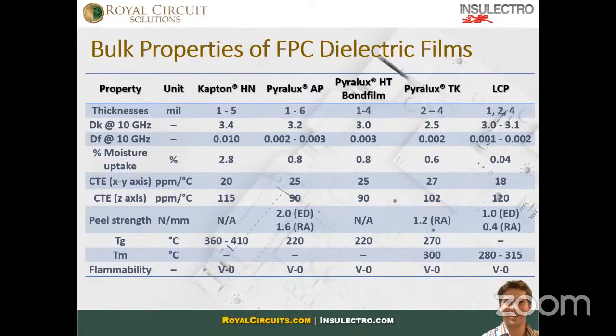You can see that standard polyimides are good, better than potentially an FR4 that might have a DK of around 4 and a DF of 0.02. Polyimide is inherently better because we don't have a glass weave running through our film. Our films are homogeneous, so the signal sees a nice consistent material as it flies from one end to the other in your transmitter. When we look at a flexible copper-clad core, such as Pyralux AP, we can see that we've actually improved our dielectrics, and we've improved the DF, which is important when we move into the frequency domain for some of those really high-speed designers out there.